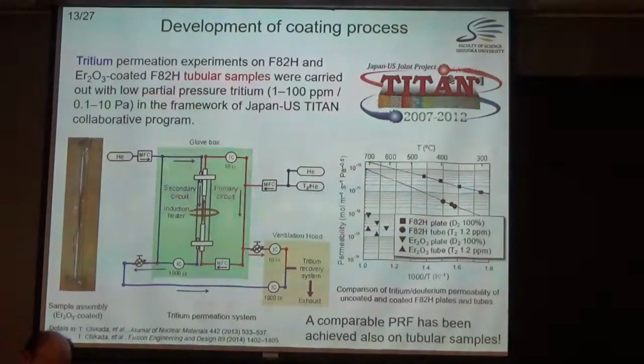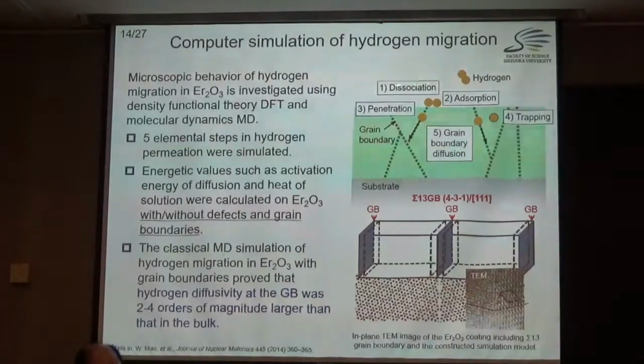Then, not only experiments, but also computational simulation has been done with molecular dynamics and density functional theory. We constructed this system where hydrogen is dissociated on the surface, absorbed, and penetrates through trapping or grain boundary diffusion. So this is a five-step migration in the coating.